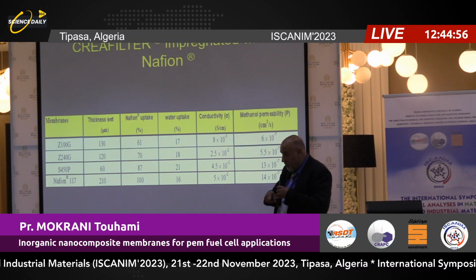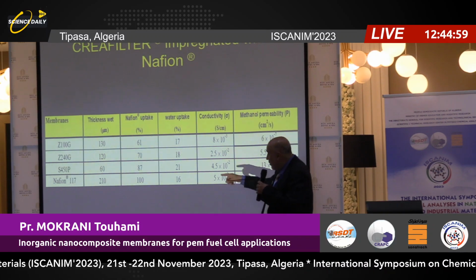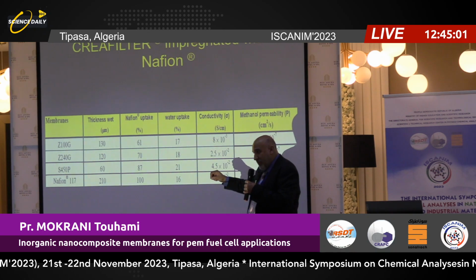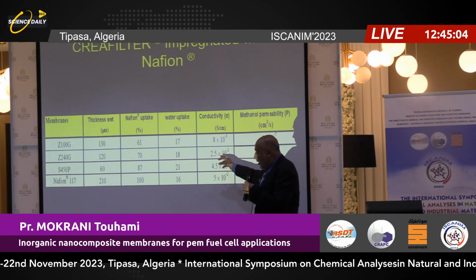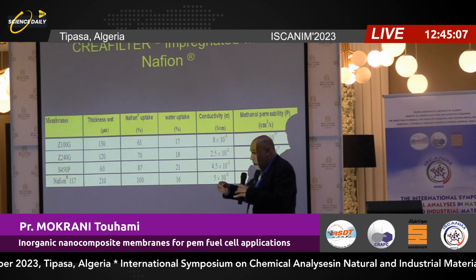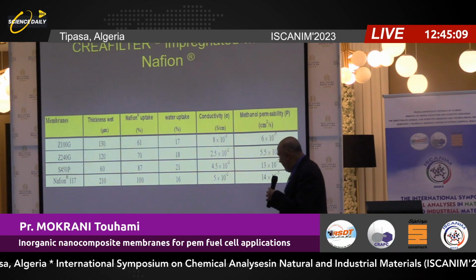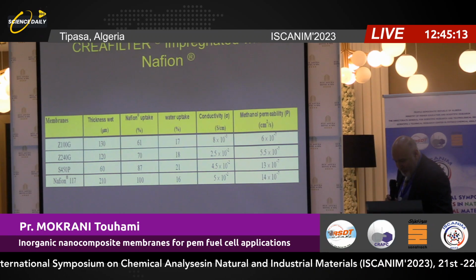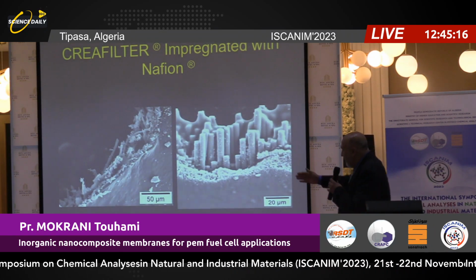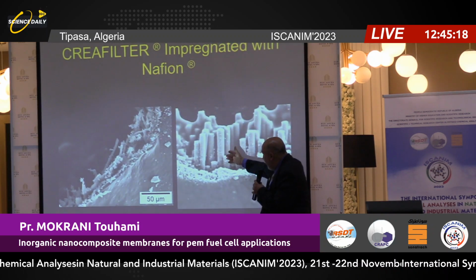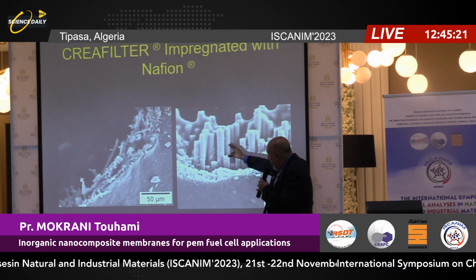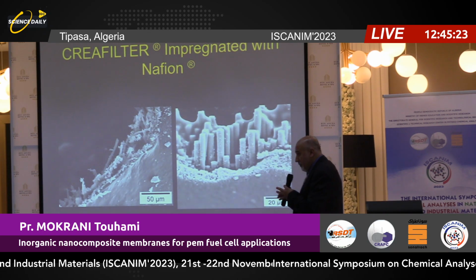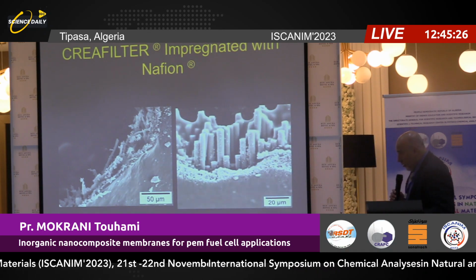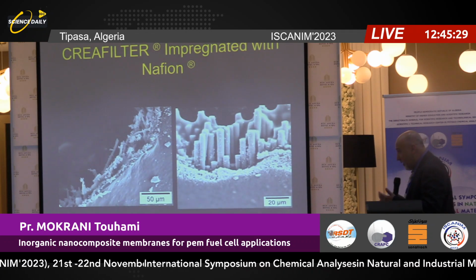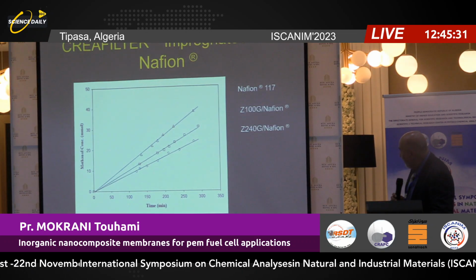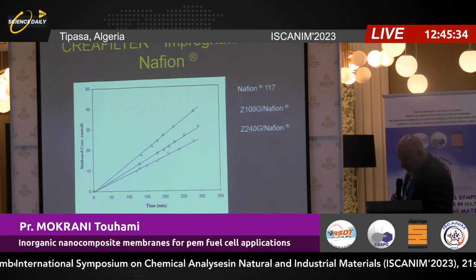So all of it is Nafion, and Nafion is very expensive. But this one is only a part, plus minus 10%, 20%, I don't know, I never calculated, but it's only a part because we take the ceramic material and we impregnate. So if we look at the same picture, you see, that's the material, but the part with this dark color is the Nafion. So you can see how much you are saving on the cost. Plus the performance, they are nearly the same, and methanol permeability is much better.